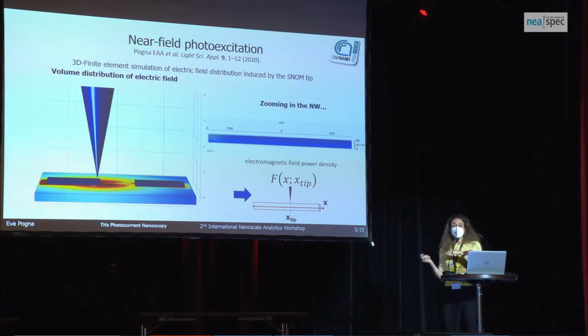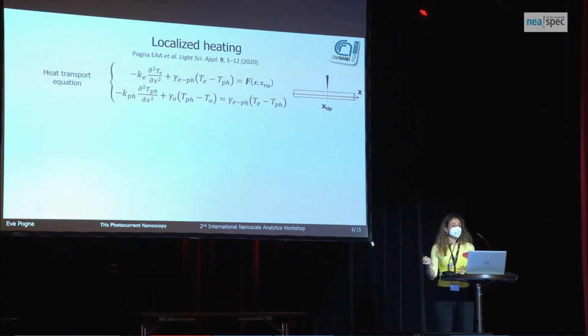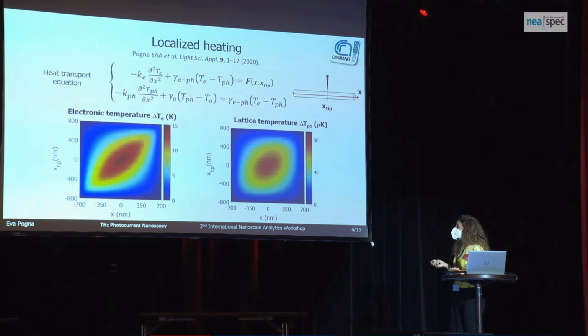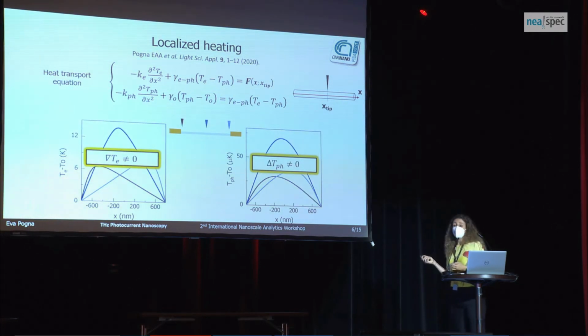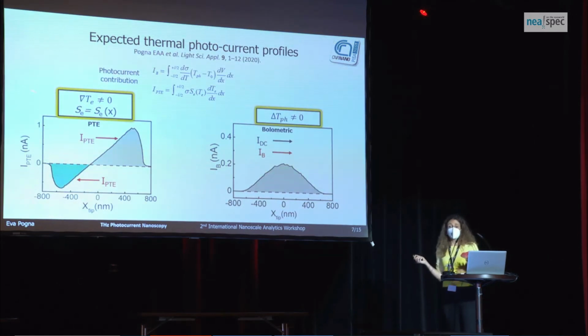And what we observe is that the energy loss in the nanowire peaks at the position of the tip on the nanowire. From that, we can solve the one-dimensional heat diffusion equation to see what is the profile in the electronic temperature and lattice temperature that result from the near-field excitation. This is the result as a function of the actual coordinate of the nanowire and the position of the tip. We can take some cuts to see what's the profile in the electronic temperature and lattice temperature at a precise position of the tip. As you can see, this local excitation is creating a gradient in electronic temperature, and it's also creating a variation in the lattice temperature. So, in principle, it's able to give rise to the thermally driven effects and photocurrents.